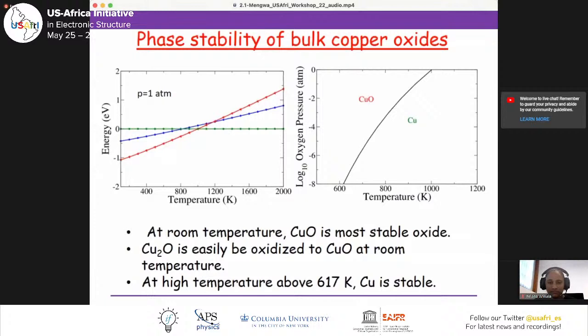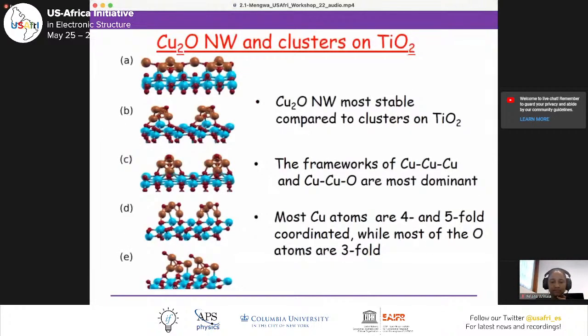You can see this when you look at the figure that has been drawn here of the logarithm of oxygen to the base of 10 against temperature. Concerning the Cu2O nanostructure and the clusters on TiO2, it's found that the Cu2O nanowire is most stable compared to clusters on TiO2.